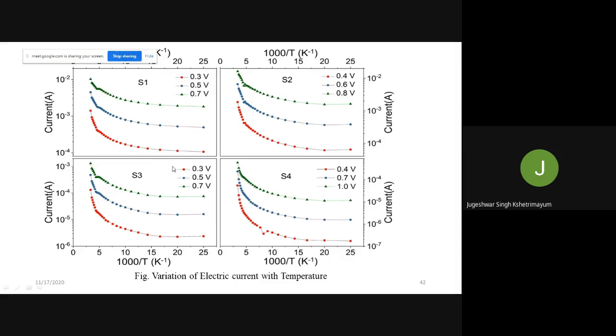This is another curve for the current and the temperature at different applied potential. We are applying the potential, we do the measurement. Okay, then what we found here is that current increases abruptly at higher temperature region. You see here this current is almost stable. Here in this section, this is stable, but in this part, this is the high temperature because 1000 by T, so in this region variation is happening. So this leads to the conclusion that different conduction mechanisms contribute at different temperature regions.